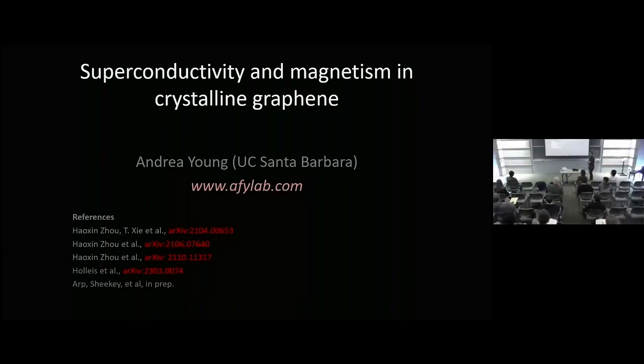Just a question from somebody who's not in the field. Is the only evidence for superconductivity that the resistance is getting unmeasurably small? You can also see signatures of phase coherence, like if you go to the edges of superconducting domes or have samples that are dirtier, you can see these Fraunhofer-type patterns. What we haven't done yet is make a Josephson junction. No junctions. We'll do that soon. But yeah, it's low resistance. It's seeing some of these Fraunhofer-type effects. It's the fact that it's suppressed by out-of-plane field extremely rapidly. It's a finite critical current. Those are the things. Yeah, these have very finite and very sharp critical currents. So that's another example.